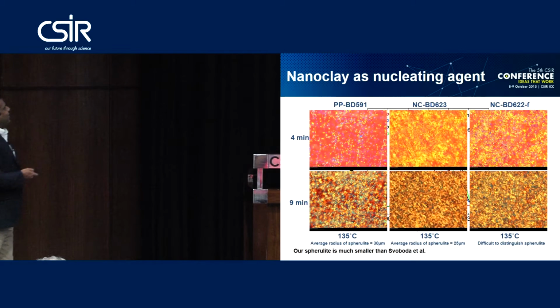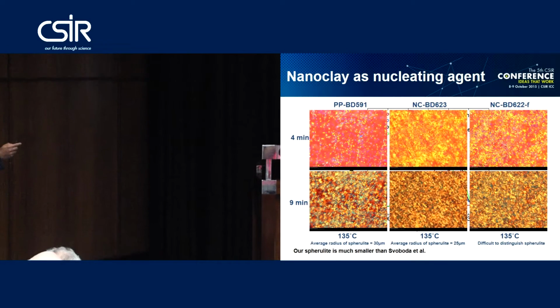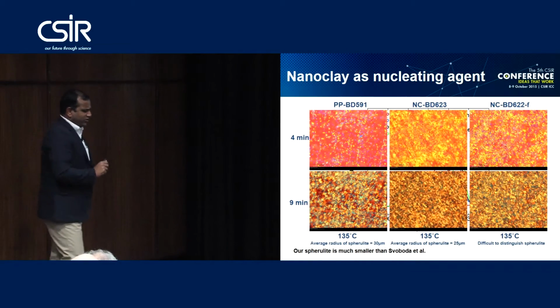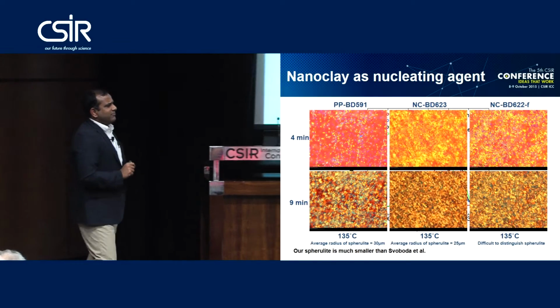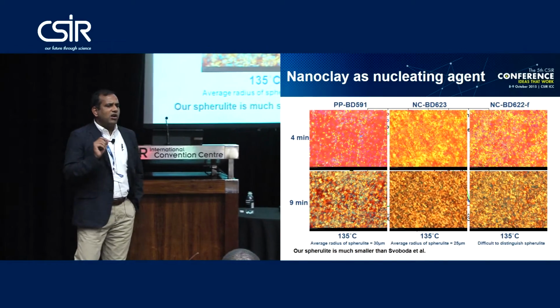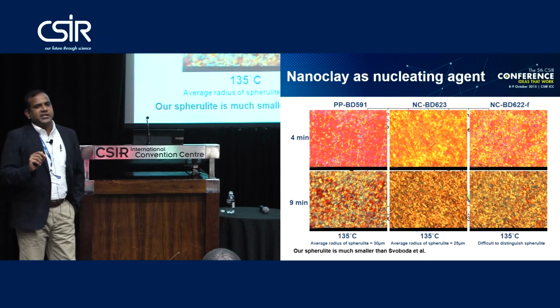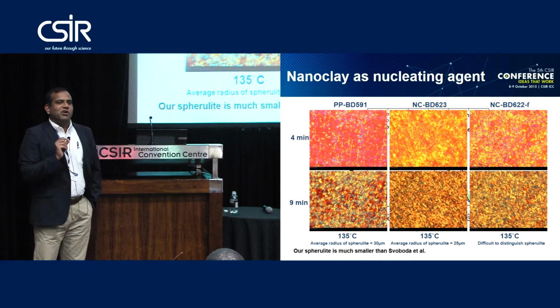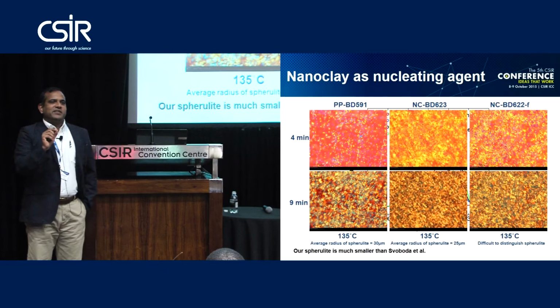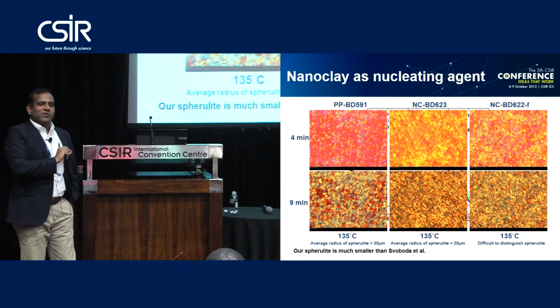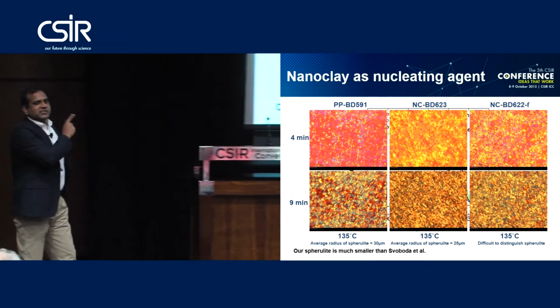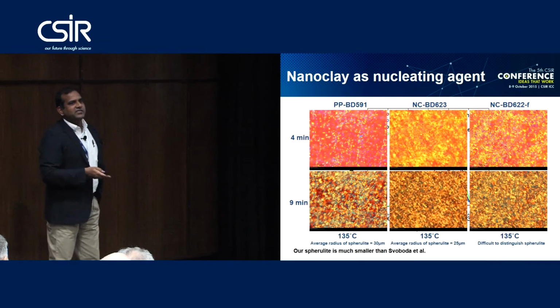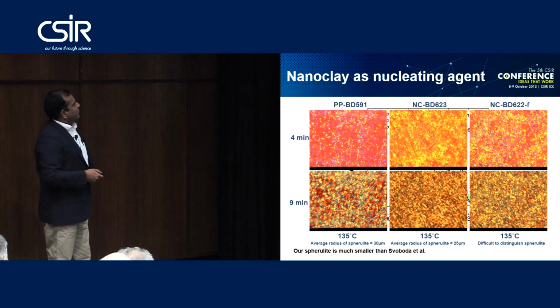So we developed a technology at the center, and we are able to increase the crystallization temperature of polypropylene by almost 15 degrees centigrade. So you can now mold polypropylene at almost 15 degrees higher temperature than the normal industry is doing, and that is a huge impact on the energy efficiency of the polypropylene molding industry.